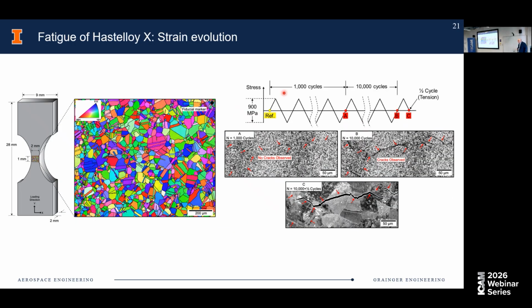So we did these types of experiments to study that. This is all still with the Hastelloy X material. We start with a small number of cycles, let's say, now we've done even smaller than this, but in this slide it says 1,000 cycles, before failure has actually occurred. This is a DIC pattern, no cracks are observed here, and we obtain the strain field. Then we add an additional 9,000 cycles, so the total is 10,000, where we actually see cracking has occurred.